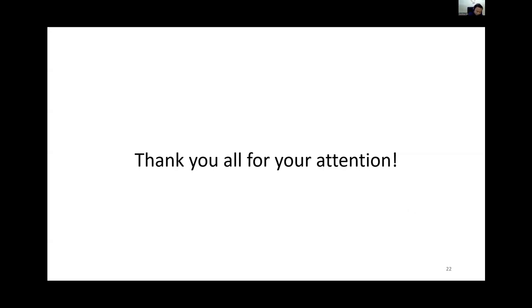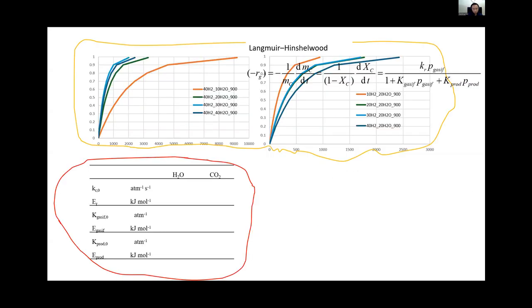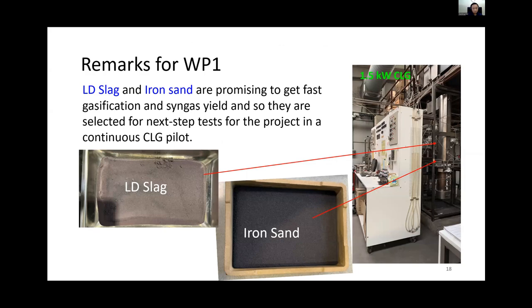Are you going to test all the oxygen carriers in the small continuous unit, or not? My plan from this batch test, I can rule out the manganese ore. So I'm not going to test the manganese ore in the continuous unit. As you can see, I have selected the LD slag and iron sand for the 1.5 kilowatt CLG unit. I'm going to use these two oxygen carriers, but also I want to use ilmenite as a reference material because not only us but other organizations have carried out experiments with ilmenite. Maybe it's a good idea to have a comparison and to understand. Maybe we can get more information. Yeah, that's my plan.